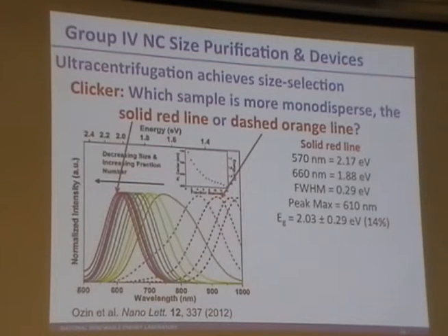And this is actually not too far off from what we observe via TEM. Our germanium particles, for instance, have 20% polydispersity. When you're looking for the perfect particles that Matt was talking about, you're looking for 0, right? Or more typically for the metal chalcogenides, the chemistry is advanced enough to where you can get 5% polydispersity, and that's really good. So when we're talking about 15 to 20, we're even less ideal. And that's going to just make Mark tear his hair out about his calculations because of our non-idealities.